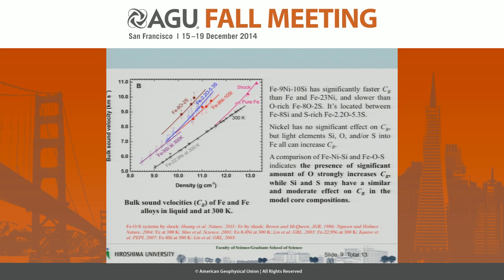Because the outer core is in a liquid state, we picked the bulk sound velocity in the molten state and compared it with pure iron, seismic data, and other molecular compositions. The result shows our iron-nickel-silicon system has significantly faster bulk sound velocity than pure iron and the iron-nickel system, and slower than the oxygen-rich iron-8-oxygen-2-sulfur. It is located between the iron-8-silicon and the iron-2.2-oxygen-5.3-sulfur.